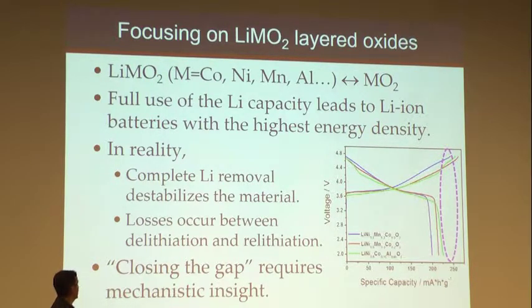But that's what reality is. You don't get to 280. The more lithium you remove beyond this point that I'm showing here, the more likely you are to have a battery fire because it's becoming really, really unstable and it starts letting go of oxygen. Not only that, when you go and delithiate and you then are trying to relithiate, the more lithium you remove, the less you get back in. There's something happening to the material that degrades it and doesn't allow you to recharge that material. So your battery will progressively lose range.